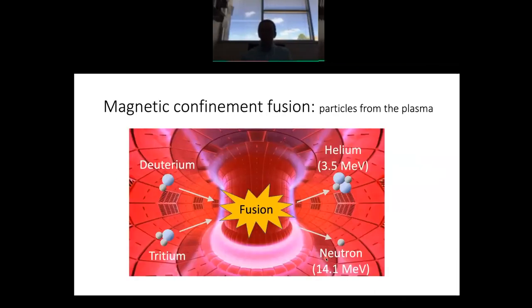Another context where this comes up is magnetic confinement fusion, where particles impinge on a material, but this time not from the material itself, but rather from the plasma. In magnetic confinement fusion, you've got plasma where, eventually once we have a reactor, deuterium and tritium are being fused and you get a 3.5 megaelectron volt helium particle that comes out. That one loses most of its energy in the plasma. So when it actually gets to the wall, it's closer to a few hundred electron volts.